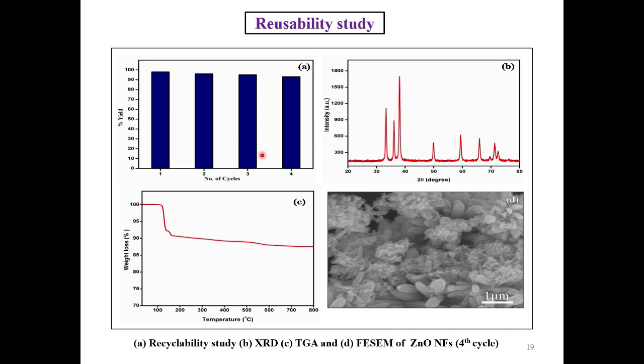Reusability study we have done, up to the fourth cycle we have gone, and when we compare from the first to the fourth cycle, a marginal decrement in the product is observed, and even in the fourth cycle the material does not lose its activity. The same peaks are observed for the zinc oxide nanoflowers as we observed in the fresh form of the zinc oxide nanoparticle, and it is thermally stable at more than 800 degrees centigrade. Somewhere there is a break of the flowers, but flower uniformity is the same throughout the structure.